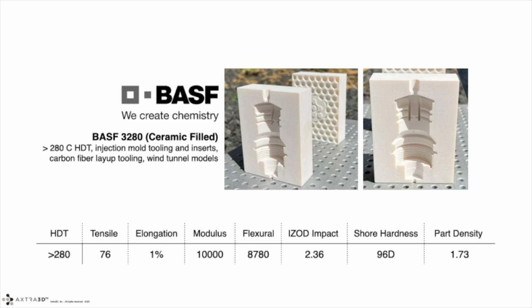Also, the cost of this material is considerably lower than competing materials in the market. And we're absolutely blown away with the performance. The exposure time on this material is less than 1 second, so it's an incredibly fast building material, and the accuracy we're seeing is sub 30 micron across the build platform. So super excited to see the new applications that we get to address with this new material. So if you've ever been looking at injection molding and been disappointed with results from different technologies, I highly encourage you to check this out.